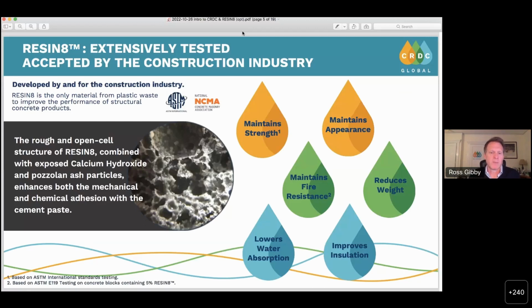And obviously maintenance of fire resistance was massive as well. Fire resistance is critical. And in fact, we've actually had tests that show improvements in fire resistance. But again, maintenance is what we talk about because it all depends on the actual mix design. But where we do get improvements and considerable value propositions from utilizing Resin 8 in concrete is reduction of weight. Our material is 1/4 of the weight by volume of sand of what it replaces. So that's considerable, either on a per unit basis or, even when we're shipping that concrete to the job site, we're seeing the ability to lower carbon footprints because of that reduction in weights.